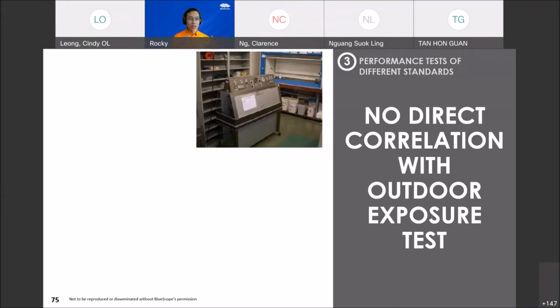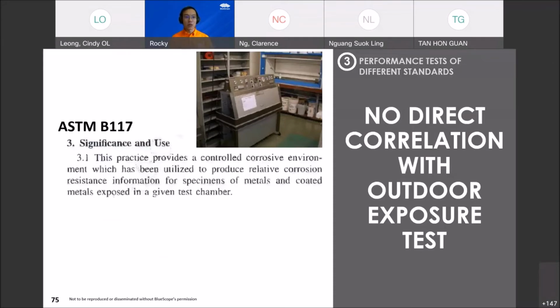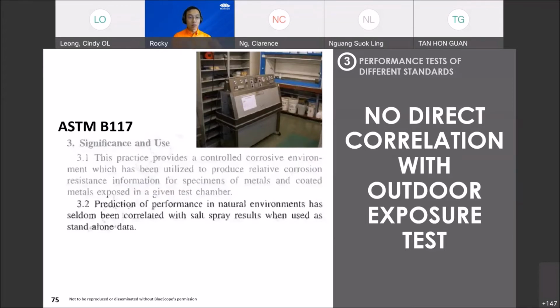Salt spray test has no direct correlation with outdoor exposure test. And why I say this is because in the test method itself, right? Take, for example, ASTM B117. It actually mentions the practice provides a controlled corrosive environment, which has been utilized to produce relative corrosion resistance information for specimens of metals and coated metals exposed in a given test chamber. And the prediction of performance in a natural environment has seldom been correlated to salt spray results when used as standalone data. Okay,